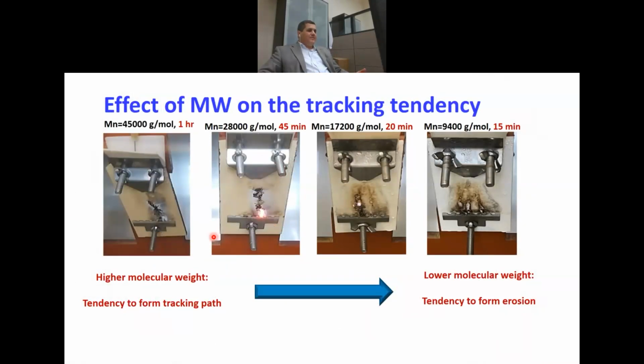In terms of the IBT test, this is the high molecular weight and this is the low molecular weight. They are not compared at the same time, but the high molecular weight seems to have a tendency to track, as you can see in this. But in the case of the low molecular weight, it has more tendency to erode. And there is a very clear trend of difference between the high molecular weight ones and the low molecular weight ones, and it is linked to the depolymerization versus cross-linking tendency, as I mentioned earlier with the TGA.